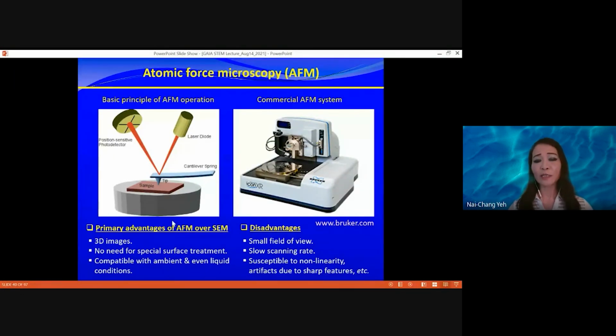Oh, by the way, you can say STM can do that too, but STM can only study a conducting surface. If your sample is not conducting, then you cannot use STM, and you have to change to AFM if you want to do three-dimensional imaging. Also, you don't need very special surface treatment, unlike scanning electron microscopy, where you have to clean your surface and do all kinds of things in advance. You can also do it even in ambient environment or liquid, but with scanning electron microscopy, you need extremely high vacuum. But the disadvantage is that it's also a slow process.